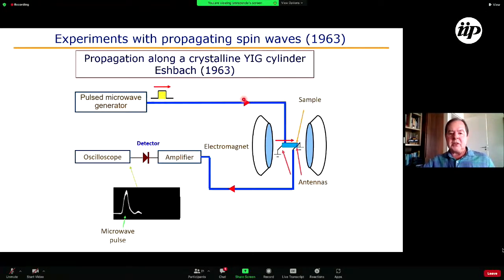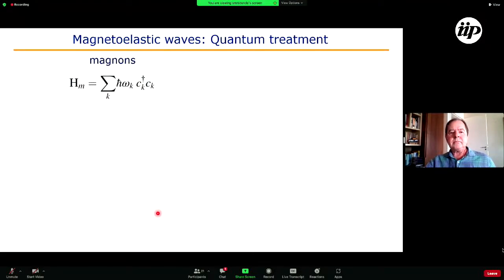One year later, he made similar experiments, not with a disc, but with a rod, a cylinder. And the experiment, again, is done with pulsed microwave. The pulsed microwave excites a spin wave in one end of the sample. In the other end, there is an antenna. This antenna picks up the signal. The signal is amplified and goes to a scope. And this is what he saw. This is the wave packet produced. I mean, the pulse produces a wave packet that propagates this way. And in the other end, this wave packet creates a microwave field that is detected by the amplifier and so on.